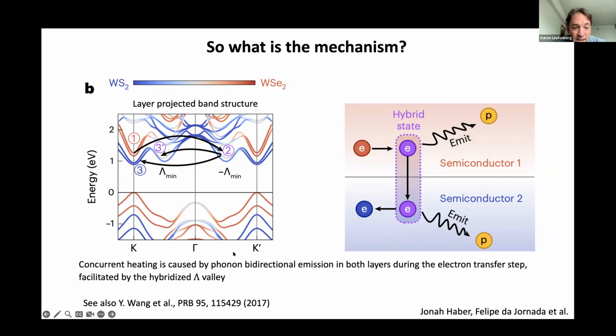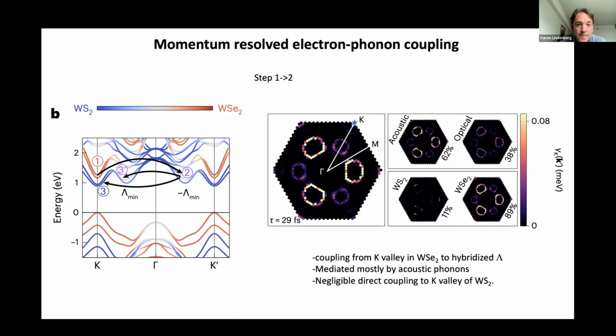Okay, so concurrent heating arises from phonon bidirectional emission in both layers during the electronic transfer step. And here are some calculations which summarize the arguments for why this seems to be reasonable. These are essentially momentum resolved electron phonon coupling calculations.